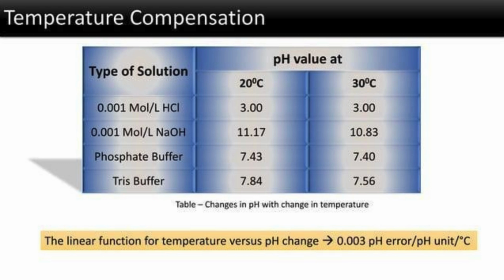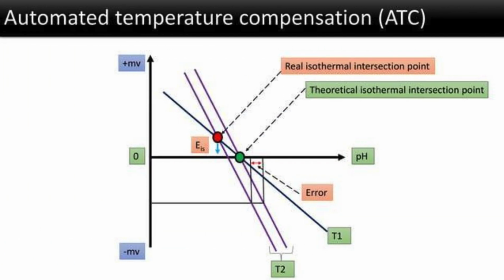The pH of a solution can actually change with temperature. For example, a 0.001 molar hydrochloric acid solution has a pH of 3.00 at both 20 and 30 degrees Celsius. But the pH of a different solution might change from 11.17 at 20 degrees to 10.83 at 30 degrees. There's a general rule of thumb, a 0.003 pH error per pH unit per degree Celsius. This is why modern meters have ATC, or automated temperature compensation. ATC adjusts the reading in real time to account for the current solution temperature, correcting for what would otherwise be an error at the theoretical isothermal intersection point.